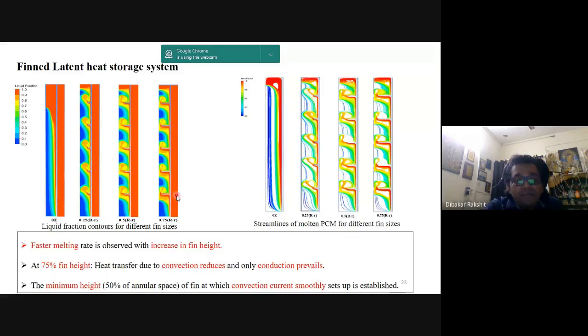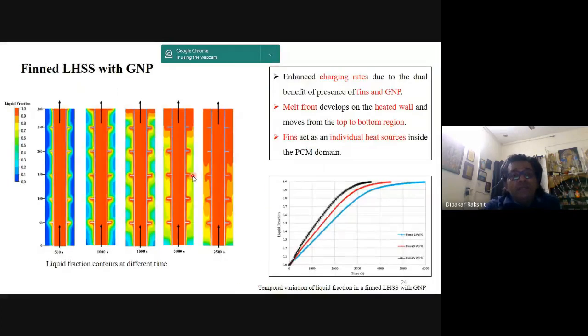Annulus means the difference between the radius of the outside and the inside, through which the hot air is blowing. So the minimum height was 50% of the annular space of the fin, at which the convection occurs very smoothly. Beyond that, if you increase it, the convection gets inhibited, and that will not be a very good situation when we are utilizing fins to dissipate the heat. So that was found through this CFD analysis.